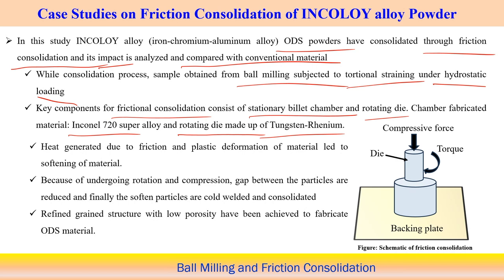And in this case, definitely when we apply the torque as well as the compressive force over the powder particles, heat will be generated due to friction, and at the same time plastic deformation also contributes some amount of heat generation. Allowing the plastic deformation will soften the material, so plastic deformation becomes easier with the application of heat. So heat is basically softening the material.